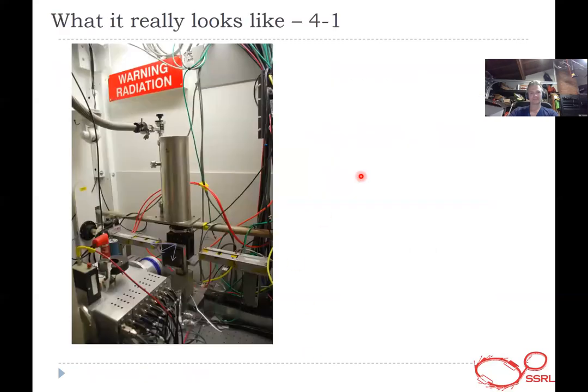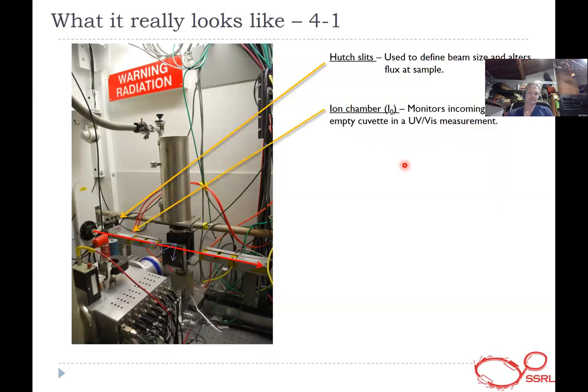And so this is what it really looks like. This is beamline 4.1. You can see that the red arrow shows the beam path, and immediately goes through some hutch slits right here. You can see these are JJ slits. They're used to define the beam size after the monochromator, anywhere from 2 millimeters vertically to 10 millimeters horizontally, down to micron size beam if it's focused and you can aperture it after that. We have an ion chamber, which is here, I0. It's your first ion chamber, and that monitors incoming flux. It's your reference in the UV-vis experiment.